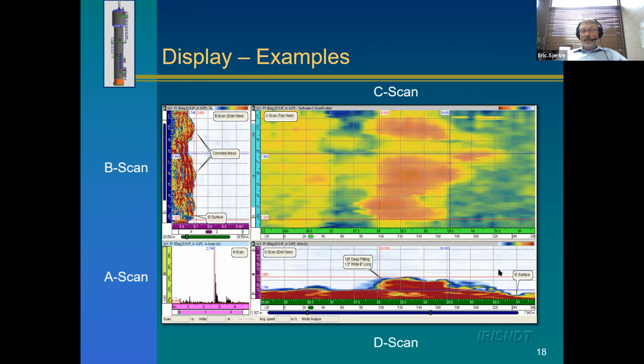So what we've done is we've taken a UT thickness transducer, which tells us the thickness of the material, and we've moved it across an XY pattern on, say, a pressure vessel. So maybe there's a part of a pressure vessel we know has some wear or some corrosion. We move it across that surface and it generates a picture of the wall thickness of that pressure vessel.